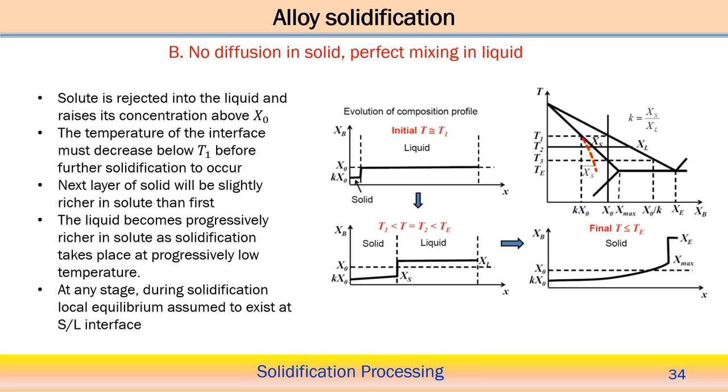So, we started at temperature T1, at time t equal to T1, where the composition of the solid phase is equal to kX0, while the liquid phase composition is X0. At T1, this is the solid phase and this is the liquid phase: the composition of the liquid phase will be X0, but the composition of the solid phase will be kX0. That is what we observe at T equal to T1. But if T equals T2, between T1 and TE temperature,